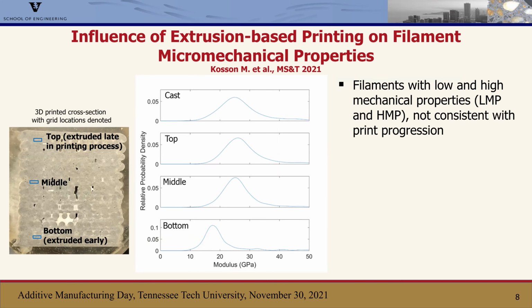When looking at the influence of the extrusion on the micromechanical properties of the individually printed filaments, what we find is that you get two types of filaments. You get filaments with low mechanical properties or filaments with high mechanical properties. And that's not usually consistent with the direction of the printing.